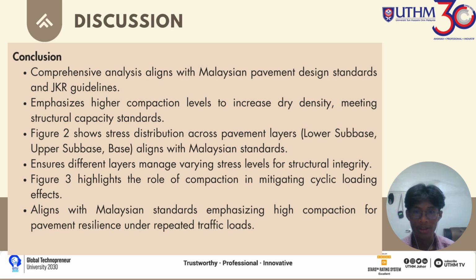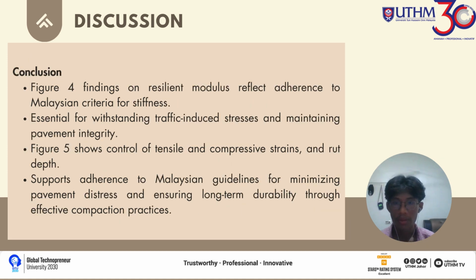For the hierarchical stress distribution, Figure 2 shows the stress distribution across pavement layers, lower subbase, upper subbase, and base, aligning with Malaysian standards and ensuring different layers manage varying stress levels for structural integrity. For mitigating cyclic loading effects, Figure 3 highlights the role of compaction, aligned with Malaysian standards emphasizing high compaction for pavement resilience under repeated traffic loadings. For the resilient modulus, Figure 4 findings reflect adherence to Malaysian criteria for stiffness, essential for withstanding traffic-induced stresses and maintaining pavement integrity.